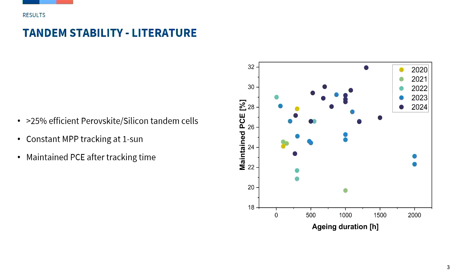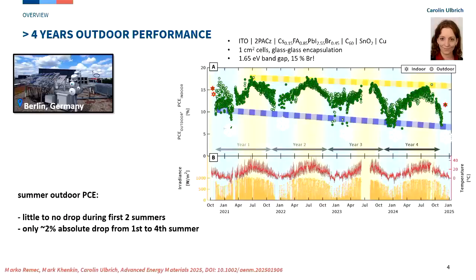Recently, we have shown, at least for single junctions, so only the perovskite, in the bad Berlin winter condition, that it's not so bad. So what you see here is the longest outdoor data that there is in literature, which we have recently published. So this is over 4.5 years of a perovskite single junction in our climate condition. Credit here goes to Caro, a colleague from Helmholtz in Berlin. So what you see is we're taking an indoor measurement, then these are 2 different cells going outdoors, and you see a summer-winter variation, so Berlin winter really is bad and our solar cells don't like it.